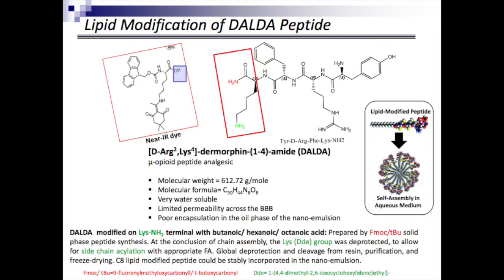The other thing we noticed is that when we modify with these lipids, these peptides self-assemble into micelles, and that micellar structure, even when present in water, has a much greater stability against proteolytic digestion as compared to the free peptide, because the enzymes are no longer able to access the amino acids and the peptide chains as efficiently due to steric hindrance. So just the fact that you create a self-assembled structure of these labile molecules, you're able to improve their stability tremendously. But we are also interested in getting these into the oil phase.